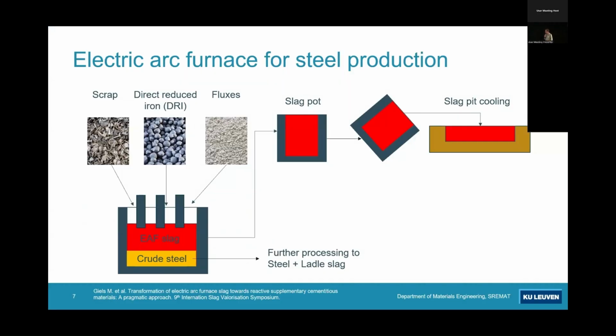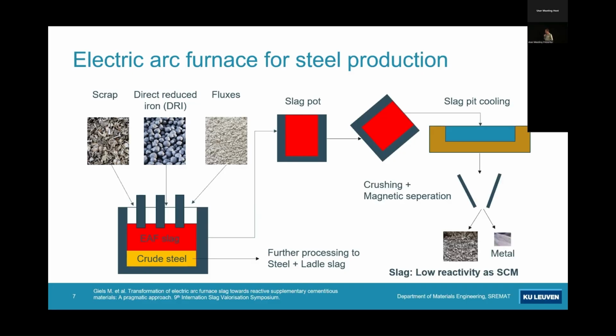Just a brief overview: you have different routes to produce steel. A very popular electric route is the use of an electric arc furnace, which Nucor in the US operates for all its plants. Basically, you take scrap, DRI, and some fluxes to produce steel in the electric arc furnace. The slag is tapped out, put in a slag pot, and that slag pot goes to the slag yard and dumps out the slag, and it cools down there. Then you crush it up and magnetically separate it to recover some remaining metals, and then you have a slag which has a very low value, mainly used as aggregate, and that tiny bit of metal.